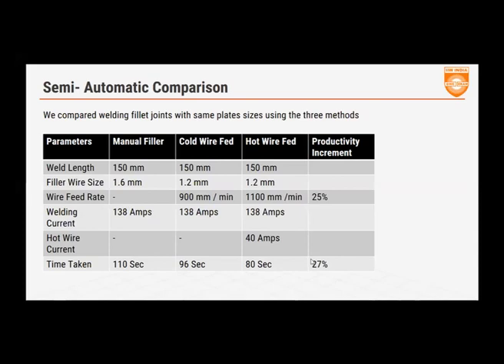If you increase this length to about a meter or more of weld length, the number of start stops in the manual process increases because the filler wires have to keep changing. This is where this will be very, very useful and can increase anywhere between 20 all the way up to 40%. The manual welder can increase his productivity.